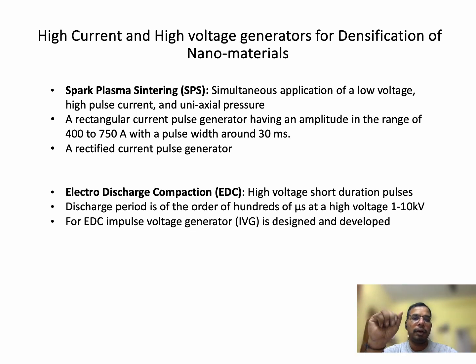a rectangular current pulse generator having a very high amplitude in the range of 400 to 750 amperes is inbuilt with a pulse width of 30 milliseconds in the laboratory. There is a second method, in which I can use a rectified current pulse generator. In this, a simultaneous application of low voltage high current pulse with a uniaxial pressure needs to be applied.